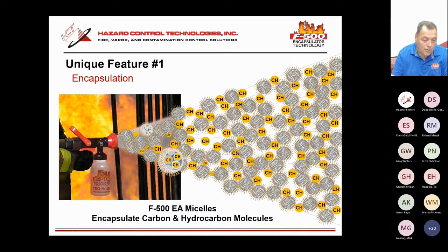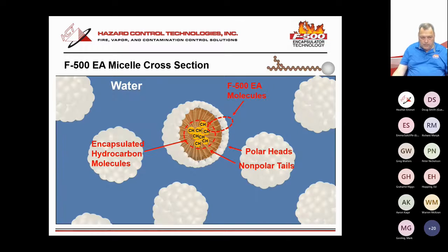To catch on fire. So that's one of the differences between F500 and the water: the encapsulator agent encapsulates any exposed electrolyte within the chemical cocoon, within the spherical micelle, thus rendering it non-flammable and non-ignitable, even if the temperature comes back, because we were putting temperature on that encapsulated electrolyte up to 1500 degrees F. So that's one of the critical things here.